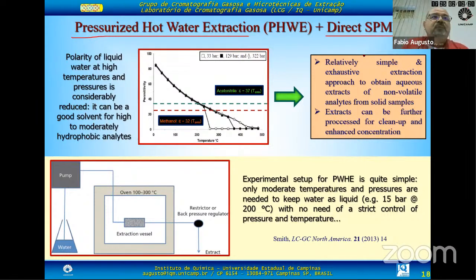Why water? Why is it illogical using water for removing hydrocarbons, for example? It's madness, apparently. But at very high temperatures, you can keep the water liquid if you pressurize it. And at very high temperatures, liquid water can be as hydrophobic as organic solvents. Properties such as permittivity, dielectric constant, etc., for water decrease with the temperature. For example, at 300 degrees, you have to keep the water at very high pressure for it to remain liquid. Water has a permittivity lower than acetonitrile and methanol. It's less polar than those compounds.